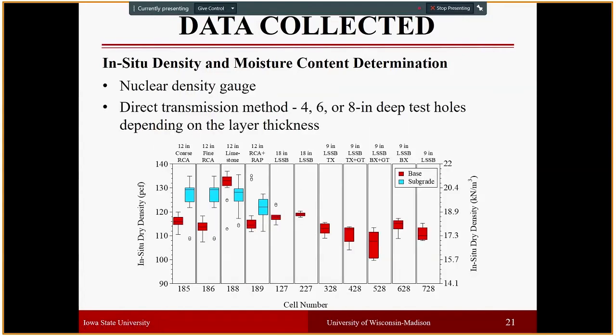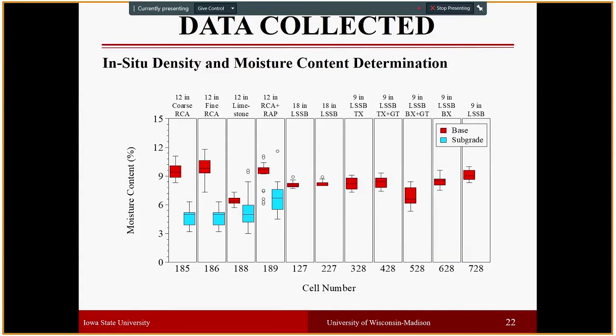And as you can see, we have the subgrade nuclear gauge density data only for the recycled concrete base layers. In terms of density of the base layers, we don't see any consistent trend. For the moisture content values, the RCA-based materials tend to have higher moisture content during construction, and the subgrade was compacted at lower moisture content values. And the base layers on top of the limestone subbases have very close or slightly lower moisture contents than the RCA test sections.